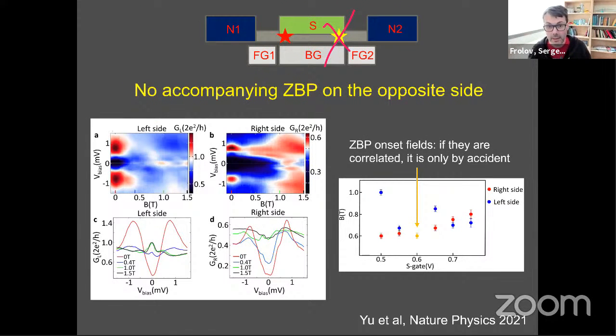And when we do that with our best fabrication practices on these devices, we just don't see the correlation. We can see a zero bias peak on one side. For instance, here on the left, we see a zero bias peak appearing at 1 Tesla. On the left, it is even of the quantized value in this particular example, or quantized value of 1 for the person who asked about that. Now, on the right side, at the same time, measured simultaneously, we see a dip. There is no peak. There is a dip. And in general, there are peaks on both sides, but they are not correlated.